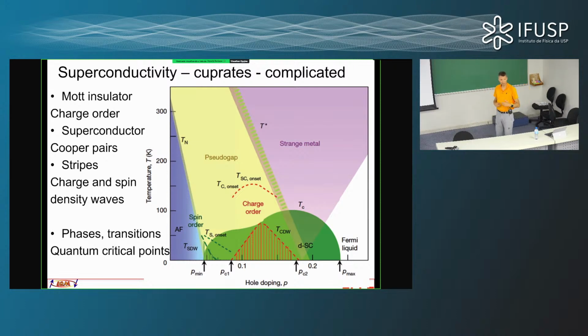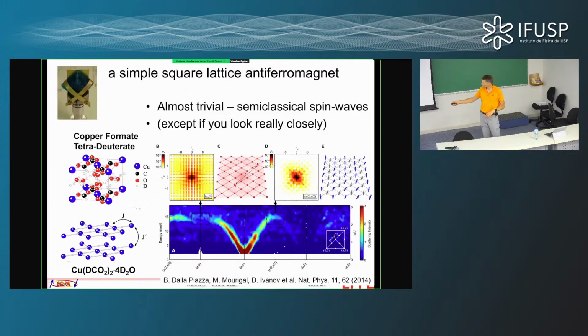Okay? Now, as a physicist, in order to understand things, one of the things we like to do is to simplify matter. So we could find a different material, another blue crystal here, which actually also has such square lattices, but where we really have exactly one electron per site, and where the ratio between the Coulomb interaction and the hopping is much higher, so that it really is very well defined, just a quantum magnet. There's no electrons hopping around anywhere. We get an antiferromagnetic ground state, and when we try to make excitations and measure them with neutron scattering, we get simple vibration of this antiferromagnetic lattice. We call them spin waves, and everything is very simple. Essentially, semi-classical theory would be able to describe that.